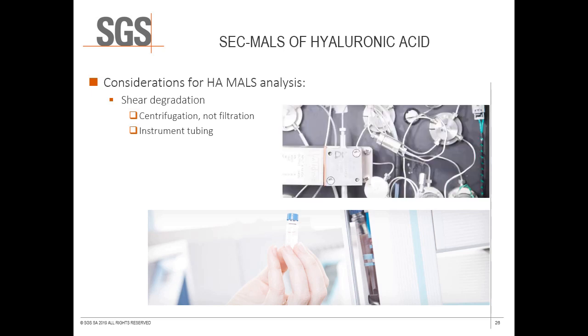Tubing with an internal diameter of less than 0.01 inches should not be used for SEC systems characterizing high molar mass species. SEC columns must be chosen which will allow the polymer molecules to separate adequately, but do not put molecules under great levels of shear stress. Columns with large packing particle sizes are recommended not only to reduce shear, but also to reduce anchoring effects.